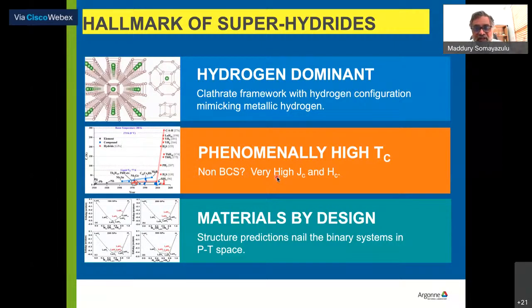Now, the question, of course, that all the superconductivity experts, people who are thinking in terms of BCS and non-BCS, would ask is: is this BCS or not? What are your typical currents? What is your typical JC and HC? Unfortunately, there are two problems here. One is that the simplest thing we can do is transport measurements. The size of the sample is so small, it's very difficult to consider other measurements, especially under magnetic fields.